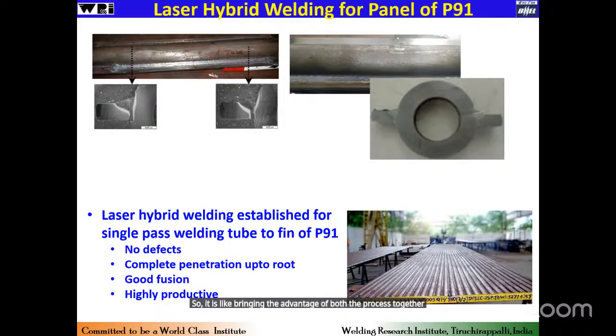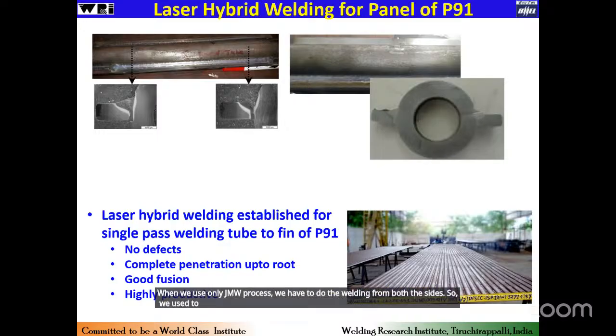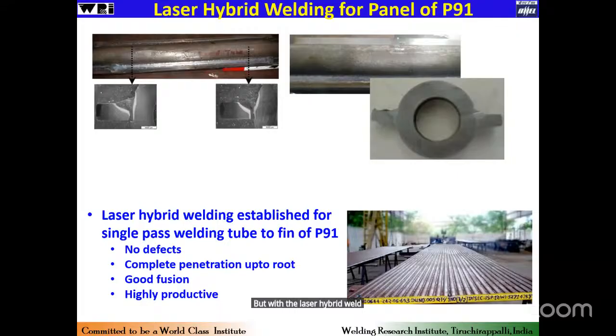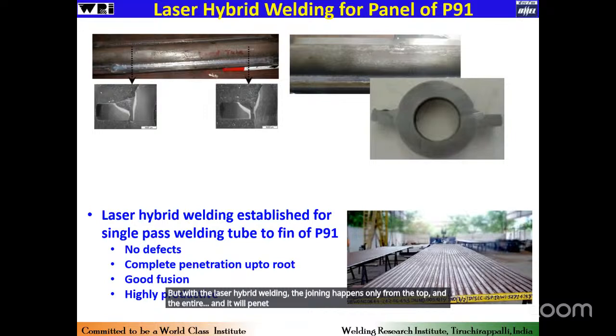So laser coupled with GMAW, we will be able to achieve the entire penetration from the top. When we use only the GMAW process, we have to do the welding from both the sides. So we used to have 10, 12, 20 torch kind of machines where the welding will happen at both the areas, top and bottom, that is a fillet weld. But with the laser hybrid welding, the joining happens only from the top, and it will penetrate through and through the entire thickness.